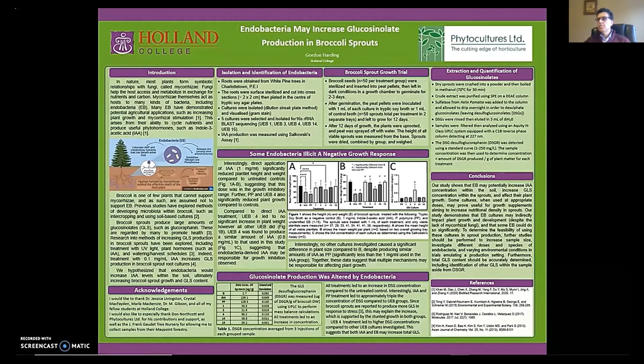Furthermore, this one culture, UEB4, produced around 0.8 milligrams per mL of indole acetic acid in the Salkowski's assay. And this was around four times as much compared to all other UEB cultures, which would likely explain the stunted plant growth. The standard P. polymyxa culture, or PP, produced around as much indole acetic acid as the other UEB cultures, shown in C, although it was able to still significantly reduce the plant height, shown here. This shows that PP probably has another method of reducing the plant growth.